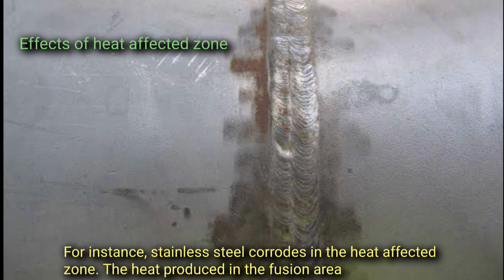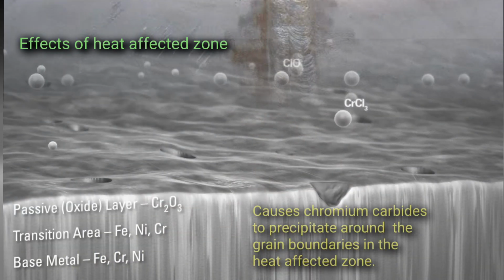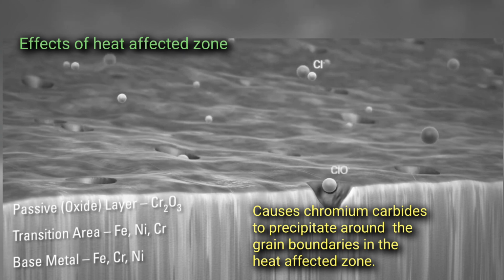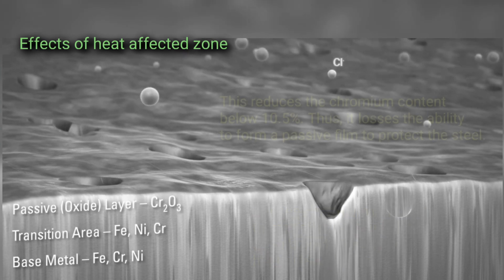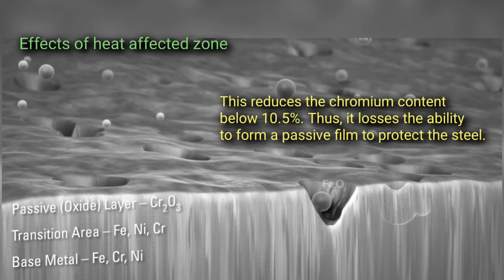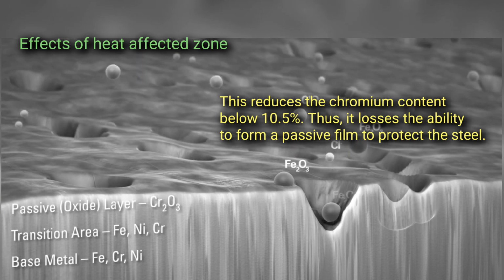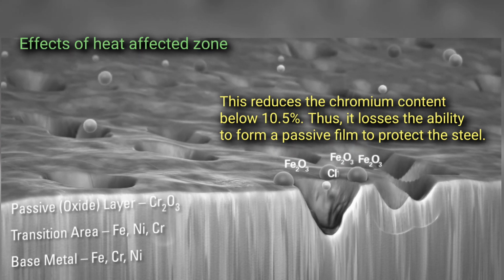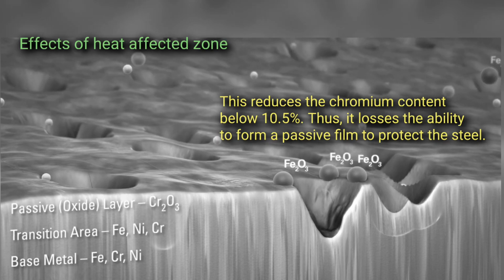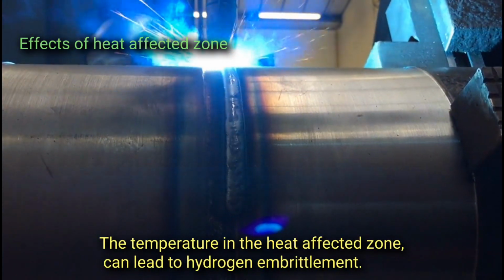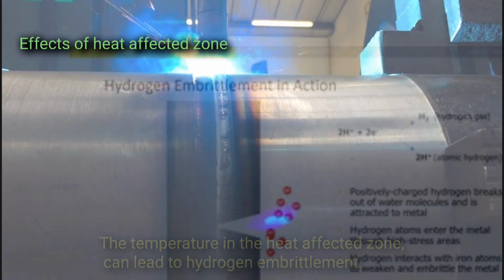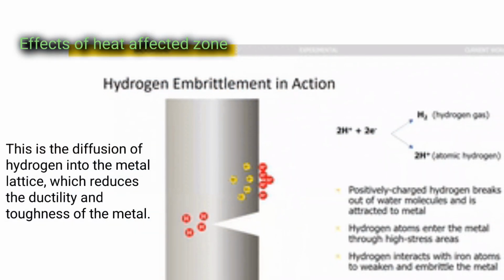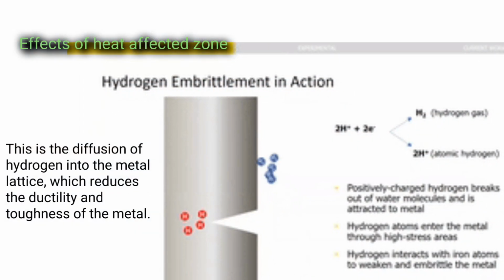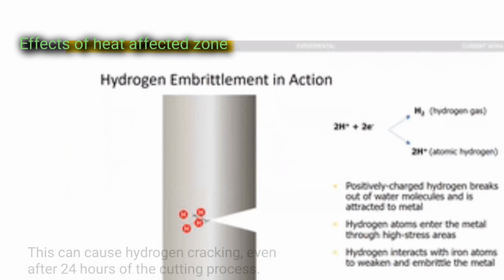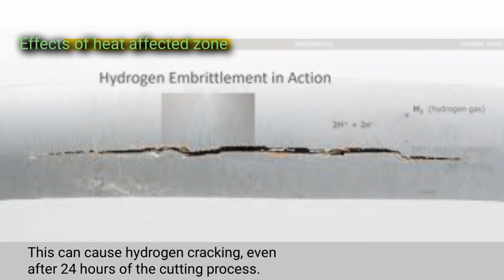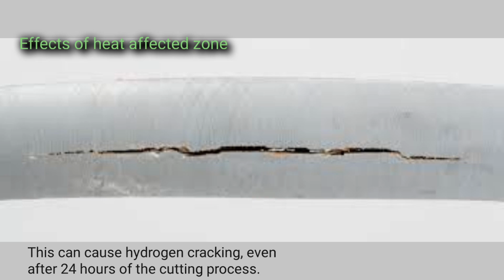The heat produced in the fusion area causes chromium carbides to precipitate around the grain boundaries in the heat-affected zone. This reduces the chromium content below 10.5%. Thus, it loses the ability to form a passive film to protect the steel. The temperature in the heat-affected zone can lead to hydrogen embrittlement. This is the diffusion of hydrogen into the metal lattice, which reduces the ductility and toughness of the metal. This can cause hydrogen cracking, even after 24 hours of the cutting process.